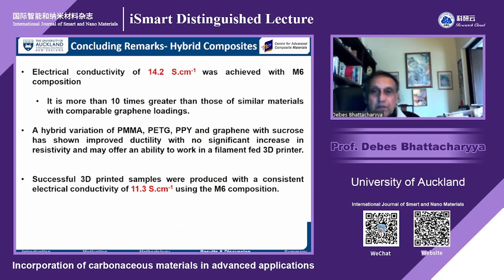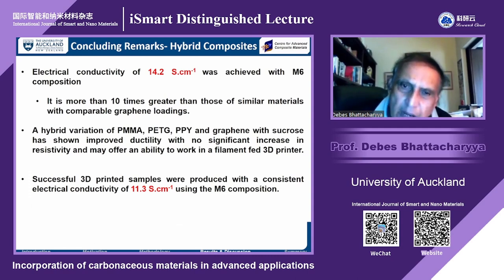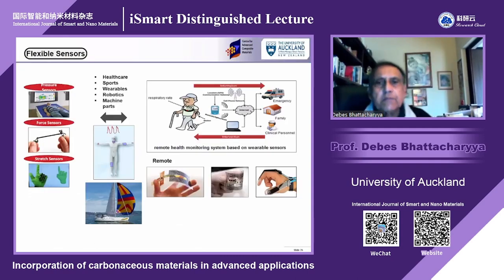Actually, your comments would be welcome there. We could not exactly figure out what the reason was. It could have been some micro cracks and some detachment there. That is why the conductivity went down from 14 to about 11 Siemens per centimeter. It was still high, but it was lower than the simple filament. But when you produce 3D printed actual dog bone specimens, we lost the conductivity slightly there. We could not identify the exact reason for that, but let us move to the next thing.